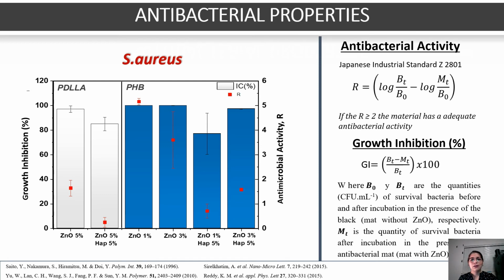Antimicrobial activity is a parameter established by the Japanese standard JIS Z 2801, used as a basis for conducting the antimicrobial study. It serves as a guide to identify if a material can be considered antimicrobial. Due to the impact produced by hydroxyapatite, the only ternary material that presented an antimicrobial activity close to the established value was PHB, zinc oxide 3% and hydroxyapatite 5%.